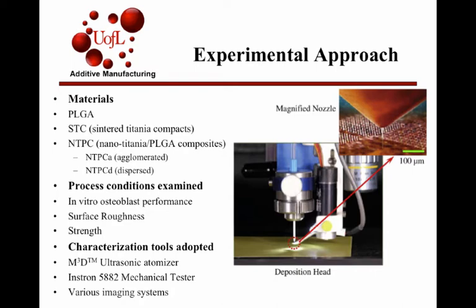So their approach, they used PLGA as a control, so we saw that when we were talking about the plastics. And then STC, sintered titania compacts, was another control, so it's just the ceramic by itself. They sintered it at 600 degrees Celsius for 2 hours. And then NTPC is short for nano titania PLGA composites. And they have two different versions of it. The first is agglomerated and the second is dispersed. The difference between those two is how they mix the titania particles. They used an ultrasound or sonication process to mix them, and at a lower power they got the agglomerated particles, so they just clumped together, and at a higher power they got the dispersed particles. So they wanted to compare the two and see which one was better.